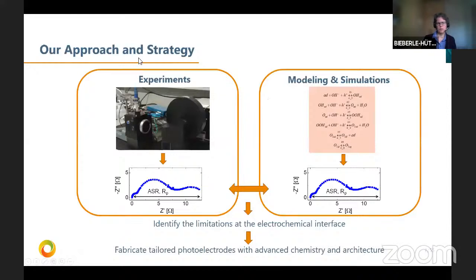And you see here, this is our approach and also our strategy. We do experiments and we do modeling. What we try is to measure the same data that we model also. So we simulate, for example, impedance spectra, and we measure impedance spectra, also current voltage curves or chopped light measurements. This is our aim. And by combining these two, we identify the limitations at the interfaces, and from this create advanced chemistry and advanced architectures with higher performance.